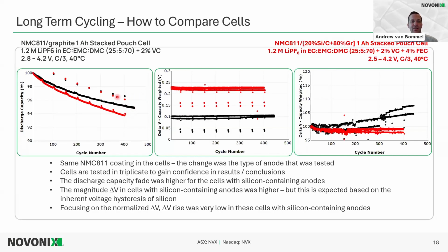And we see here that the discharge capacity fade is higher for those cells containing silicon than those graphite-only cells, and this is expected from what we see. But the silicon-containing cells are quite excellent. It's fairly close to the cycling of that graphite-only cell. So we're seeing much improvement in these silicon-carbon based materials.